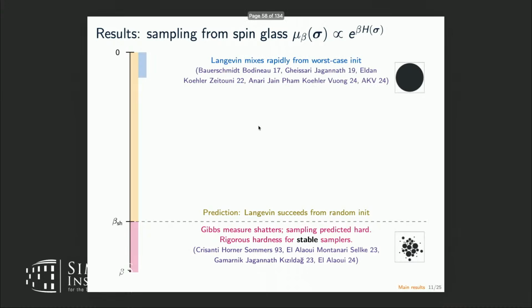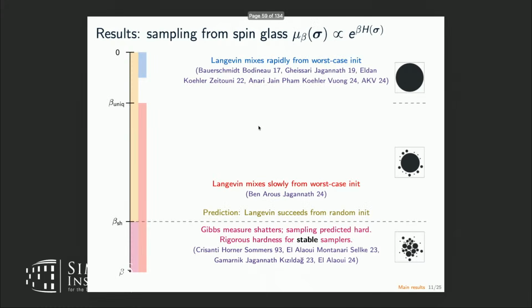In the way of rigorous results, it's known that at small enough beta, so high enough temperature, Langevin dynamics will mix rapidly from even a worst case initialization. It's also known, due to a recent paper by Ben Arous and Jagannath, that above a threshold beta uniqueness, there indeed exist metastable states. So anywhere above this beta uniqueness, Langevin dynamics will provably mix slowly from a worst case initialization. And this beta uniqueness is a natural barrier for many analyses of Langevin dynamics, because often when these analyses work, they also show rapid mixing from worst case.